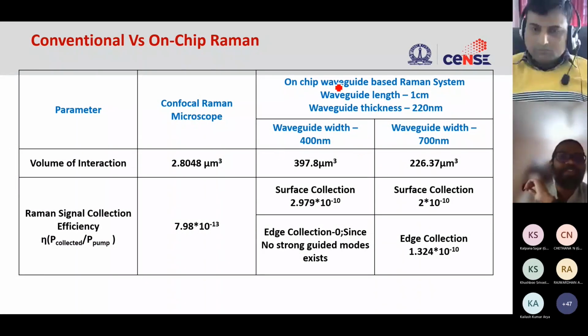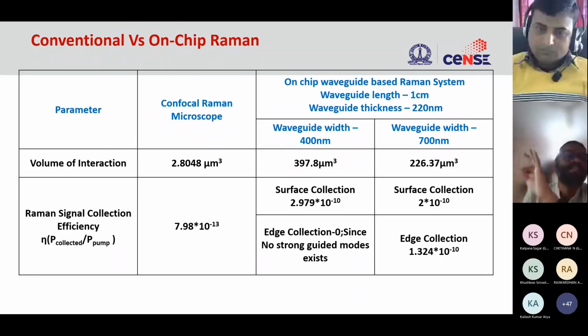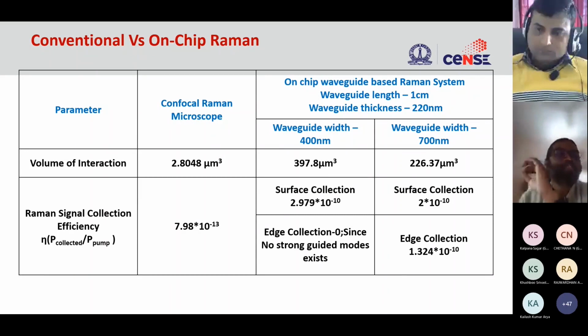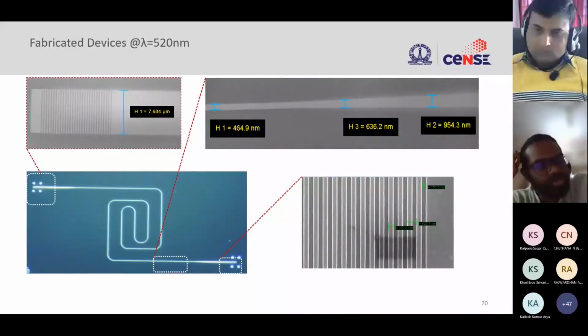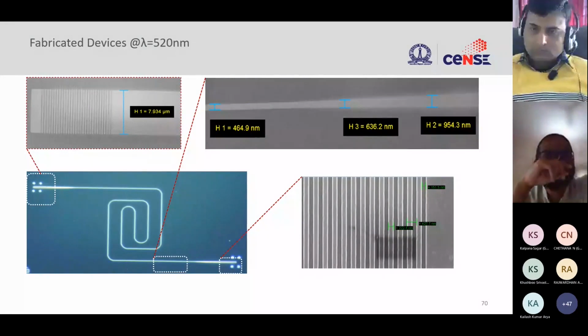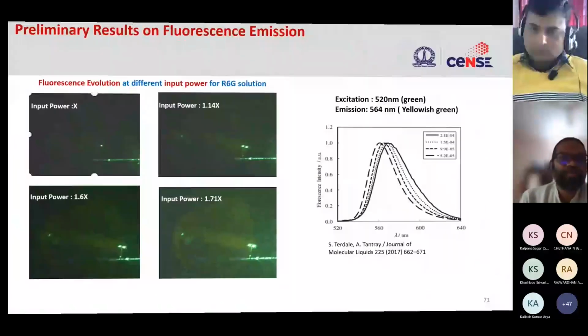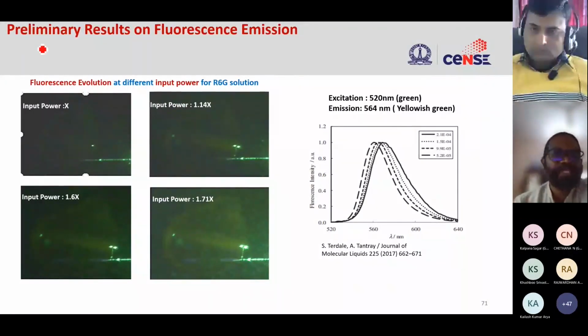However, in a guided wave, on-chip waveguide system, you can get anywhere between 200 to 400 micrometer cube. You can already see that it is 2 orders of magnitude larger interaction volume, and that improves your collection efficiency as well. You can see here the collection efficiency is 3 orders of magnitude better. So based on this, we tried to do these basic measurements at 520 nm in this case, to make these waveguides and see whether we can couple the light in and generate any signal.